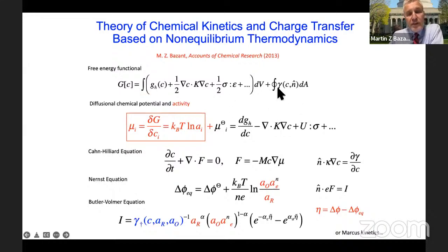So once you have a free energy, the chemical potential, which is the change in the free energy of adding a particle, is the functional derivative, or variational derivative, the first variation of this functional with respect to concentration. And that's very well known and is widely used in thermodynamic or phase field type modeling. But the new part in my work is to really connect this back to chemistry.